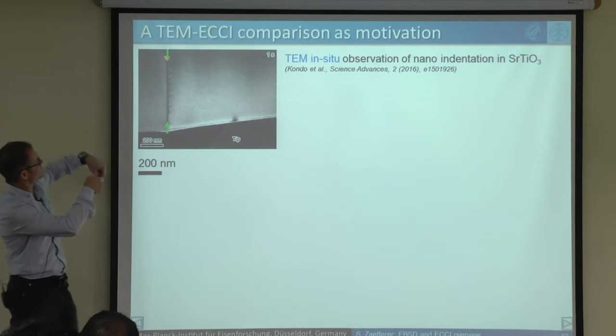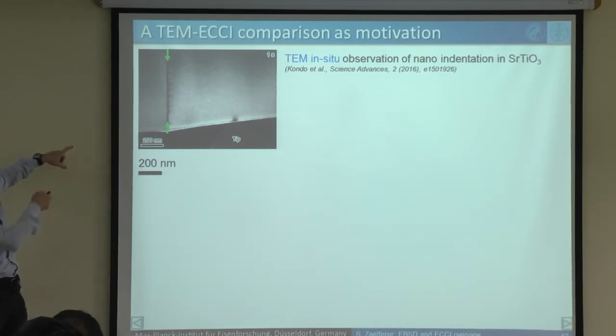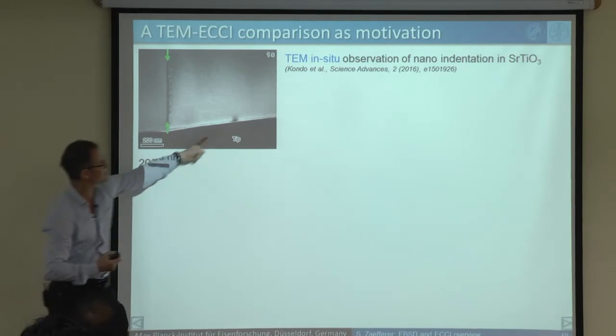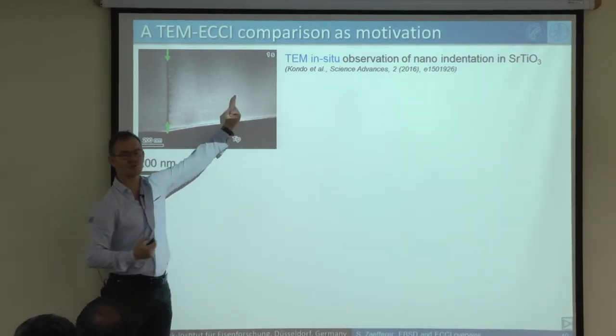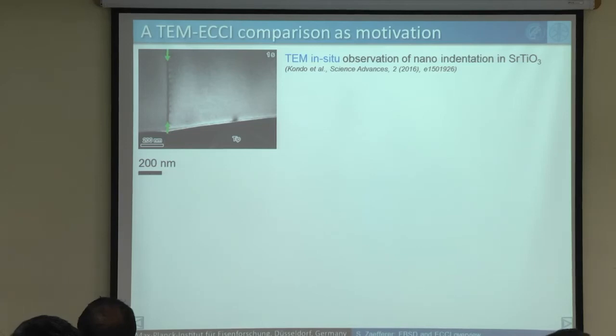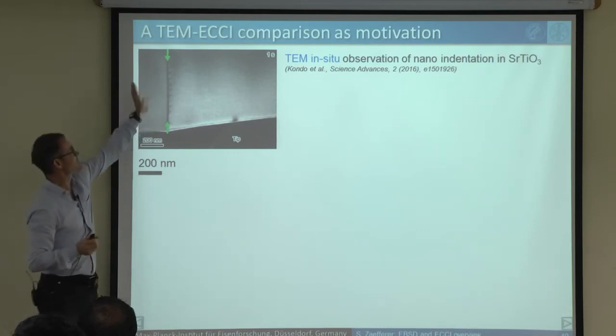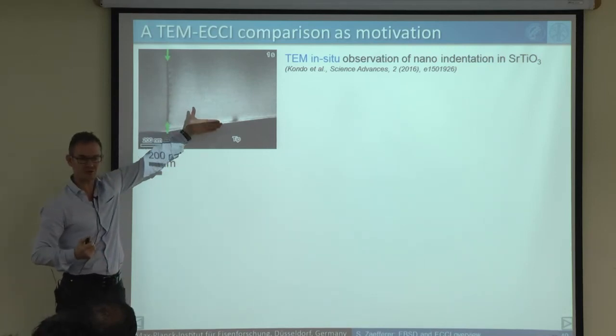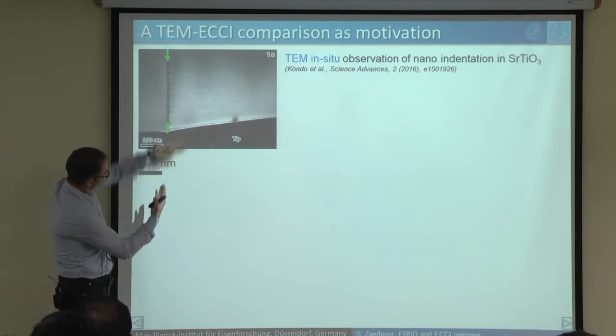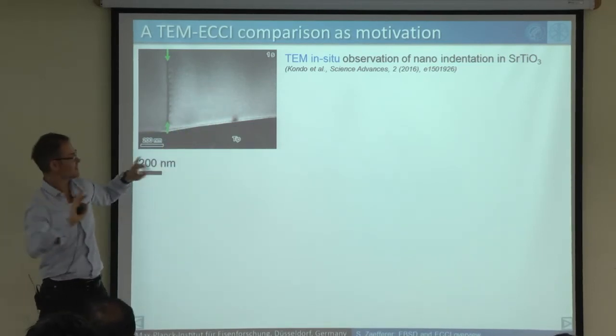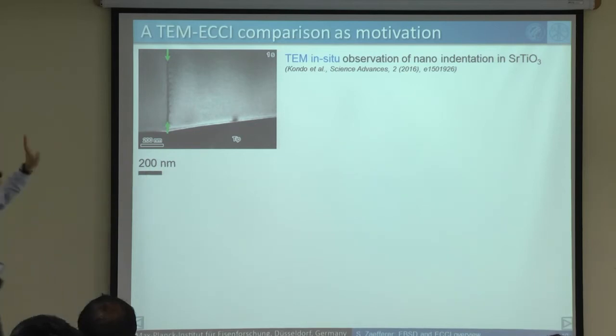So you have here a bicrystal. Here's a grain boundary. Here's one crystal. Here's another crystal. Here is an indentation tip, an indenter tip, which is now pressed into the sample. And you can observe in situ, more or less, what the indentation is doing. This experiment is very demanding. This is a beautiful experiment. I'm certain they have worked for months on this experiment to get a proper bicrystal with the right two crystals, nicely oriented with respect to the indenter, then the indenter coming right straight onto this thing here and having the sample not falling down, not breaking, and everything beautiful.